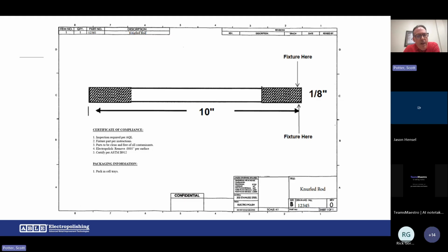Here's just a mocked up drawing. If we figure on fixturing on the knurl, it's a good place to hide our rack marks. And then just some practical notes on there. Electropolishing, removing 5/10,000 per surface, so it'd be a thousandth diametrically. And then we're certifying to ASTM B912. And then they've got packaging in cell trays. Cell trays are something that we do a lot, where the parts are actually put into an individual cell, and then the trays are stacked. It just depends on the fragile nature of the part.